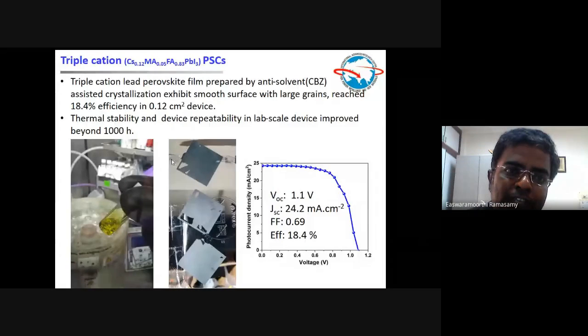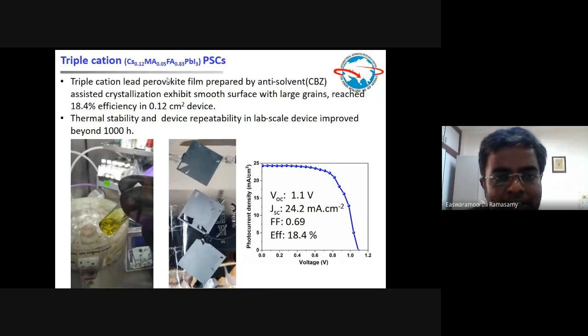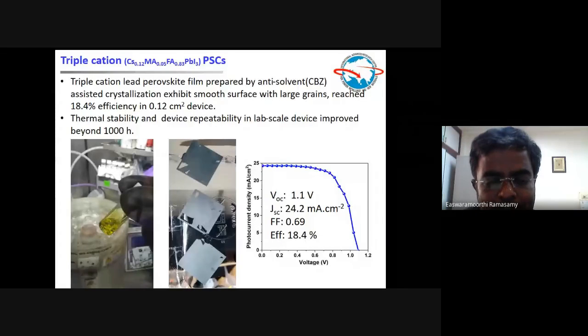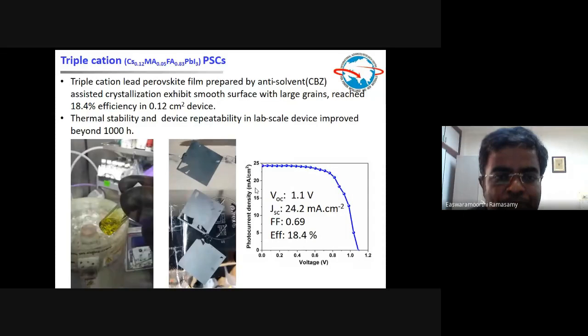But later we moved to multiple cations, because you can add whatever possible candidates inside the solution to play with the material's crystal structure, optical properties and electronic properties, and you can introduce your new invention to further improve the efficiency. That is the concept behind our R&D activities, and we made this. You can see that 18.4% efficiency was one of the best numbers from our laboratory. The world record for this cell is about 24.